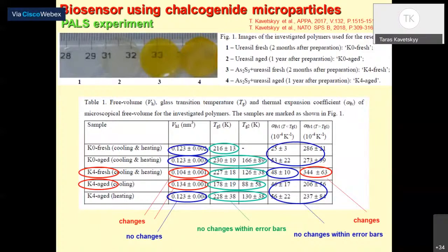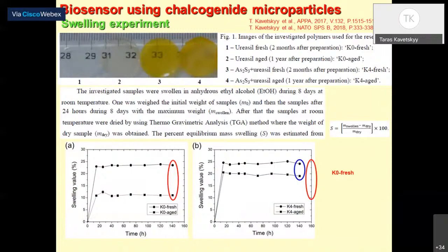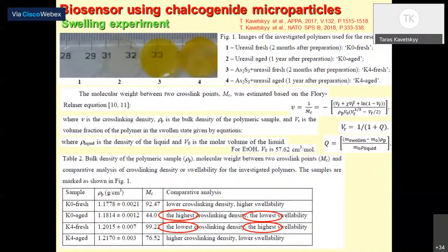After evaluation of the positron annihilation parameters, we found that the largest difference in thermal expansion coefficients below and above Tg is observed for the K4 fresh sample. Next slide. Also, similar results were obtained using swelling for these four matrices. Next slide. When we compare, we see that among the four polymers, the K4 fresh sample has the largest free volume, or the lowest crosslinking density. Next slide.